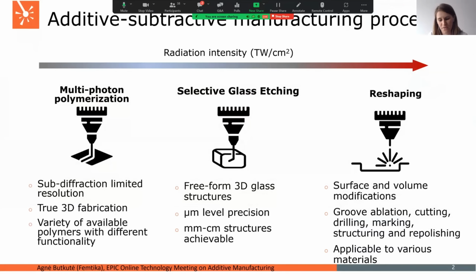In general, Femtika provides femtosecond laser-based microfabrication solutions. By using a single laser source, we're able to do a few different techniques. Just by tuning the laser radiation intensity, we're able to do multiphoton polymerization, which is an additive microfabrication technique which allows fabricating 3D structures out of polymers. By increasing radiation intensity a little bit, we're able to do selective glass etching, which is a subtractive microfabrication technique, but in that way we're able to make arbitrary shape structures out of glass. And with a higher intensity, with the same femtosecond laser source, we're able to do reshaping, so some kind of ablation, marking or structuring of various materials.